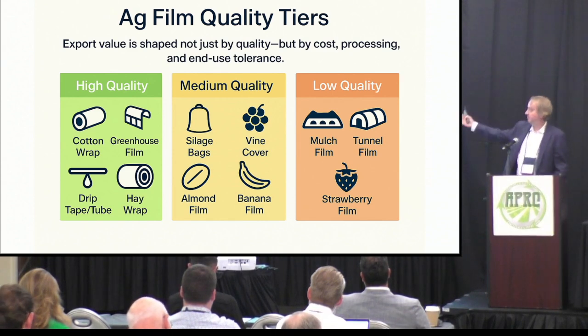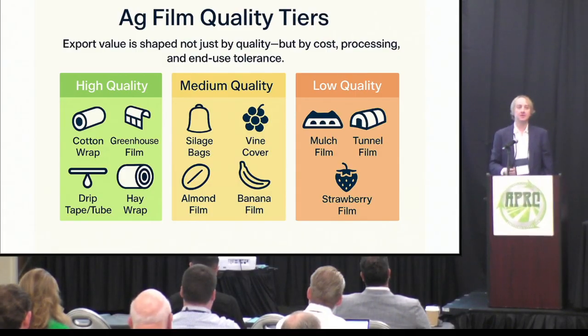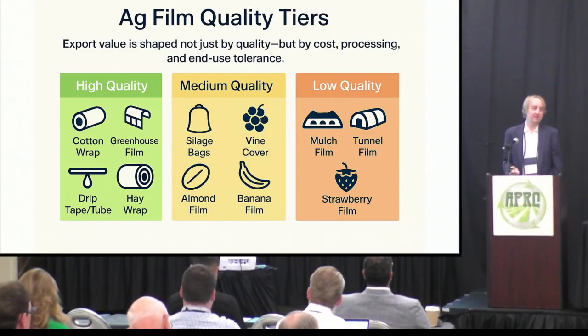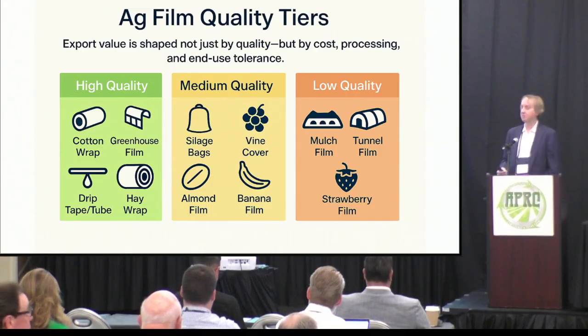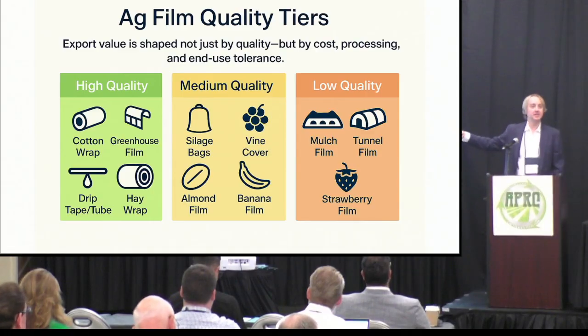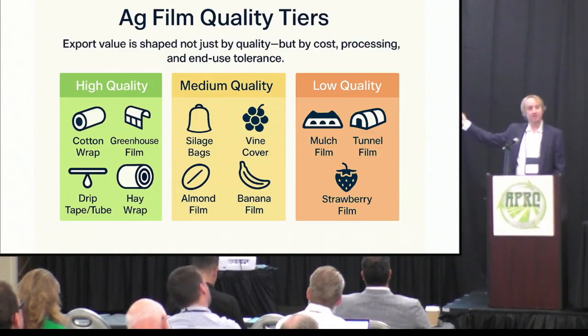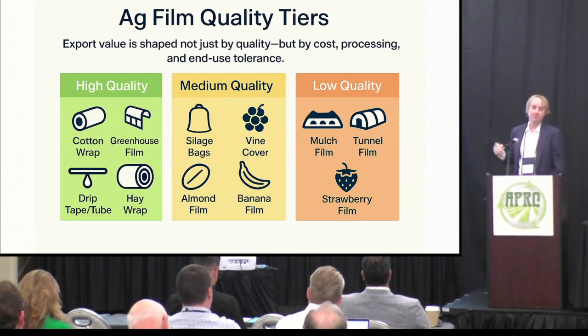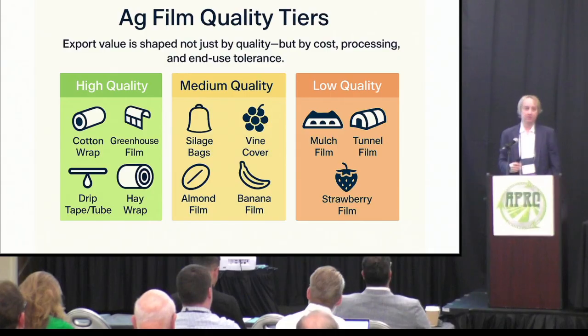Then you have a lot of materials in the middle, such as banana film, almond film, silage films. Those would kind of typically be materials that from a mechanical recycler standpoint might yield 50 to 70% range. And then you have a lot of low quality materials, such as mulch film and strawberry film and tunnel film, and these are typically low yielding materials. And so historically speaking, it was always the high quality materials that would move first and easiest, and then a lot of the middle grade materials. And your low grade materials would either move not at all or very, very little.